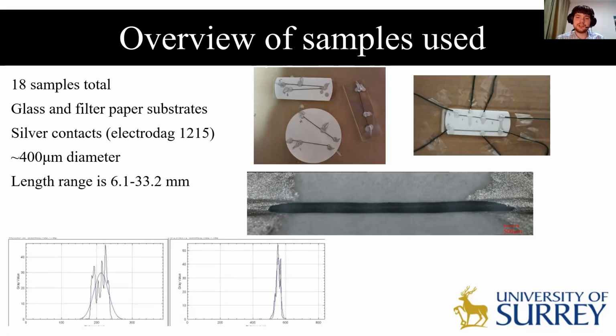I had to prepare a new set of samples. I've made 18 in total, using mainly glass and filter paper as my substrates. I've used the same silver contacts as used in the previous sample, and I have found through image analysis with ImageJ that my wires were somewhere in the region of 400 micrometers in diameter. Also, their lengths ranged between 6.1 and 33.2 millimeters. Overall, this gave me a pretty good sample with relatively constant diameters and a variety of lengths to work with.